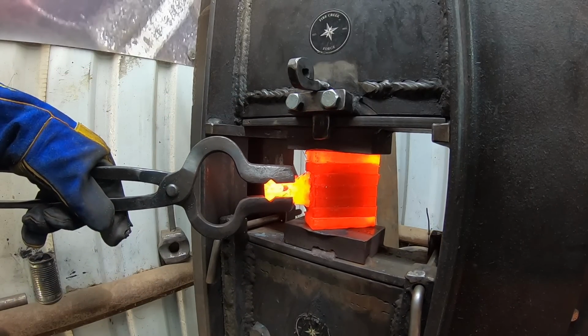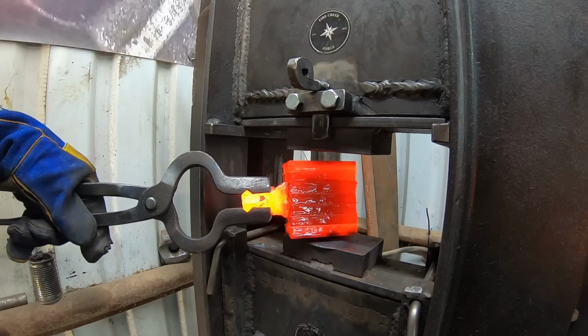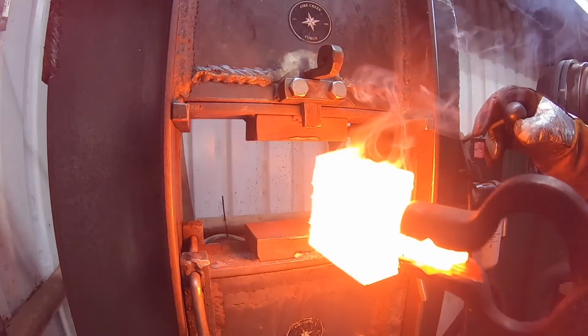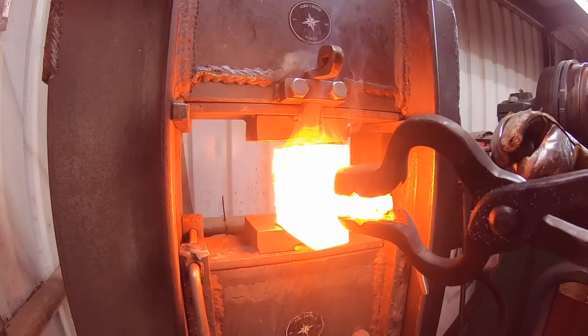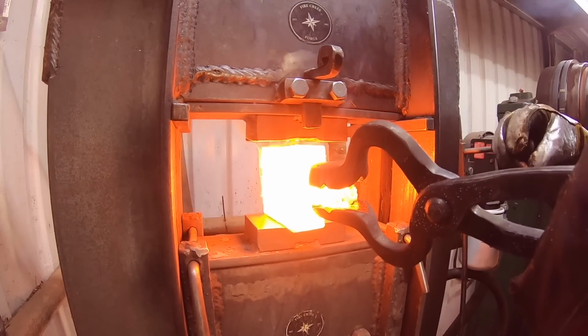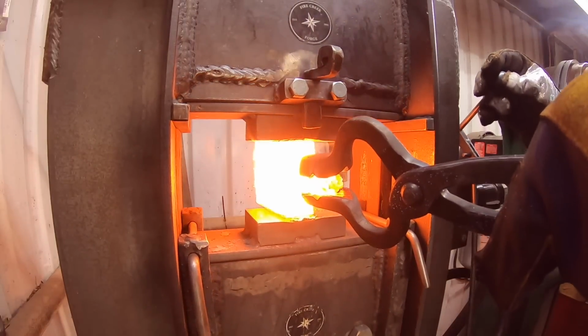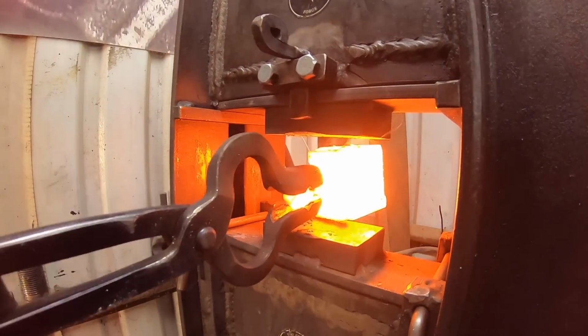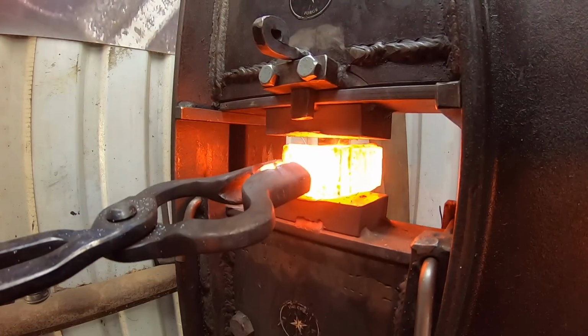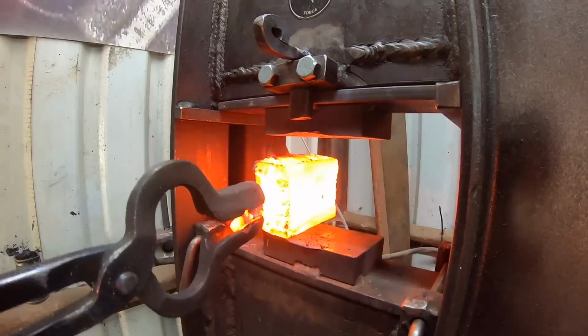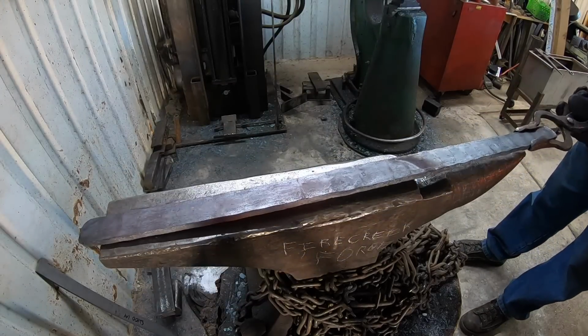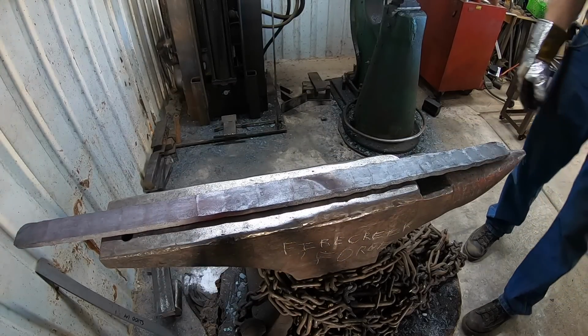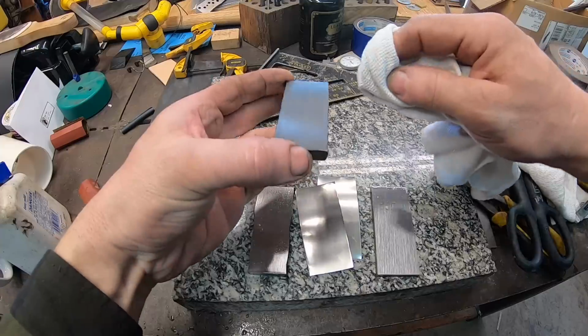So on this one, I decided to compress the stack just a little bit as it was heating up to eliminate some gaps, and then of course go ahead and set the forge weld. The flux that you see there, you see me putting on the white powder, that is borax, and that's necessary in an open atmosphere forge welding situation.